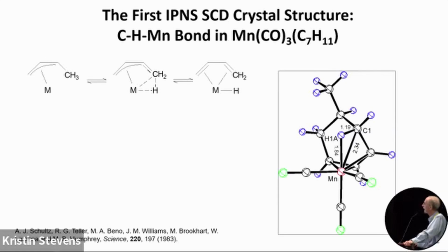So this manganese molecule from Maurice Brookhart's laboratory was the first experiment on the IPNS SCD. So we collected data, but then the structure wouldn't refine using the X-ray model. And we were very anxious about this. Teller and I went through all our code to see if we made any mistakes. And we asked Mark Beno to try to solve the structure by direct methods. And he was able to do that. And we discovered that we had indexed the peaks with a non-standard unit cell, which metrically looks similar to the standard one. Anyway, once we corrected for that, the refinement went normally, and it was a very good refinement. So that worked out well in the end.